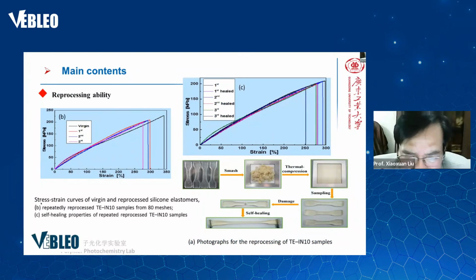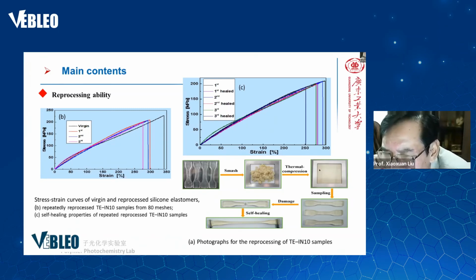Regarding the stress-strain curves of the virgin and reprocessed silicone elastomers, A is photographs of the reprocessing of the TE samples. So it is the simple pictures. So it is a smart pattern material, with small pieces heating and pressing to reform the film. To prepare the sample, it requires damage and cutting into two parts and self-healing together.